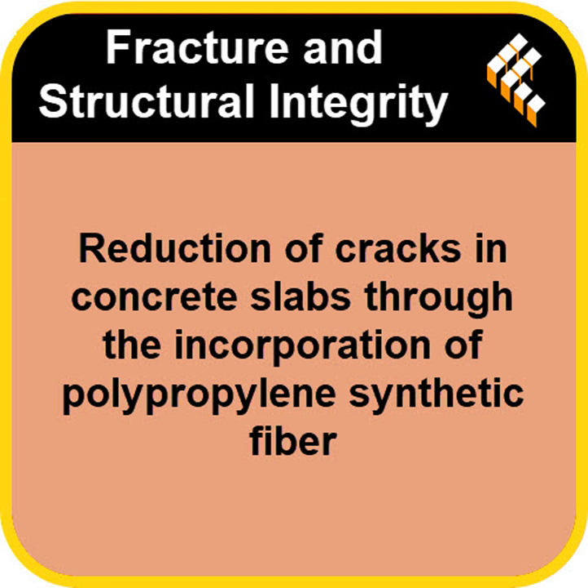It all goes back to that dosage dilemma. A high concentration of fiber got in the way. It ruined the concrete's workability. It created voids. And when the slab shrank, those defects opened up into much wider, more dangerous cracks. The concrete basically rejected the reinforcement. It did. It makes that middle dose, the 1,000 grams, look like a really delicate sweet spot.